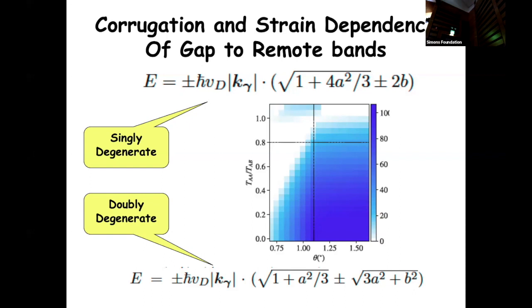And so it turns out that at the center of the Brillouin zone, I'll be showing a lot of in a minute, in twisted bilayer graphene, the gamma point of this Brillouin zone, that's where the electrons come from furthest apart, from 300 millivolts away as a function of twist angle, to become nearly degenerate near the Dirac point. And it depends on details, on the ratio of AA to AB tunneling, whether when these bands come together, they come together as doubly degenerate pairs, which would mean that there's no energy separation between the flat band and the remote band, so-called, at the gamma point, or they can come together as singly degenerate levels.